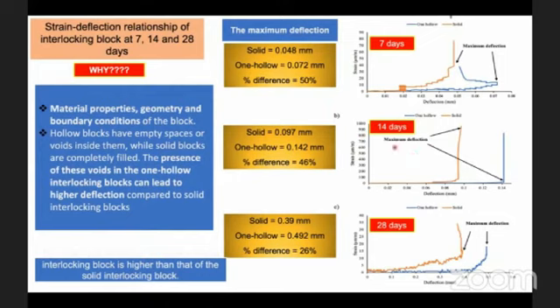And then at 14 days, for solid it is 0.097 millimeter, and for the hollow it is 0.142 millimeter. The difference at this age is 46%. And then the maximum deflection for solid at 28 days is 0.39 millimeter. The hollow interlocking block is 0.492 millimeter, with a percentage difference of 26%. So in this case, the deflection of the hollow interlocking block is higher than that of the solid interlocking block.